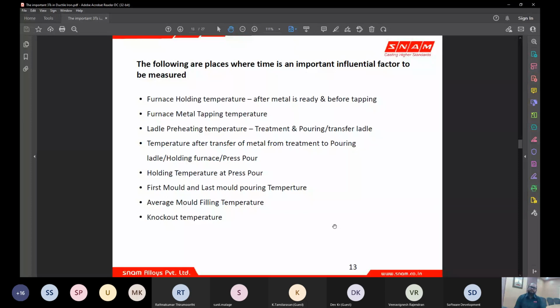Then comes the holding temperature at press pour. As we have seen, when the holding temperature is very high, the property loss in the liquid metal is going to be very high. And then the average of the first and last box, or last mold, pouring temperature. When your pouring temperature varies drastically between the first mold and the last mold, your casting is going to cool in a different way, and as the casting cools differently, the cooling rate has a different effect on your microstructure, and thereby on the properties of the ductile iron castings.